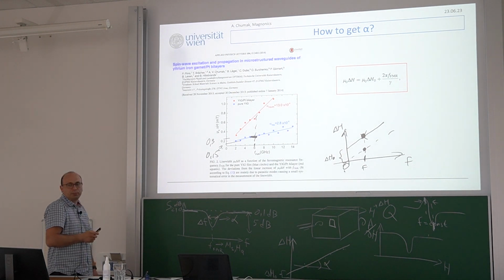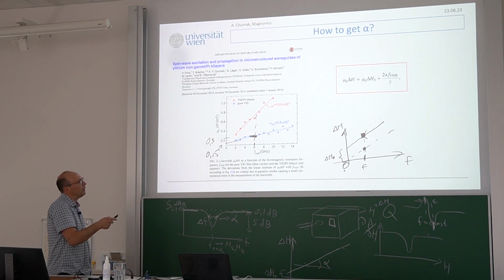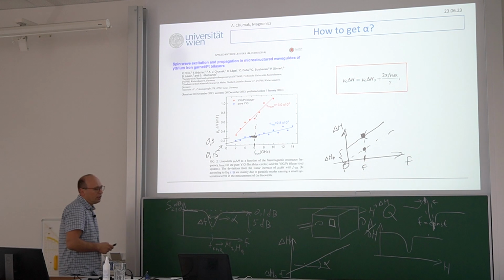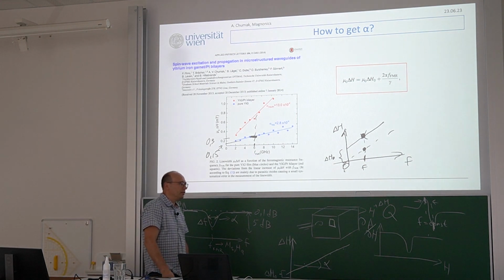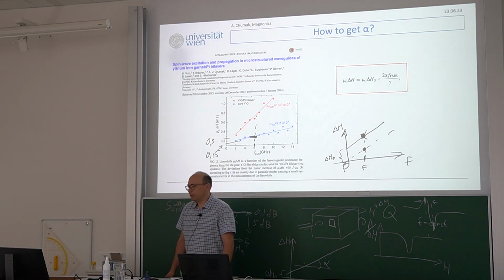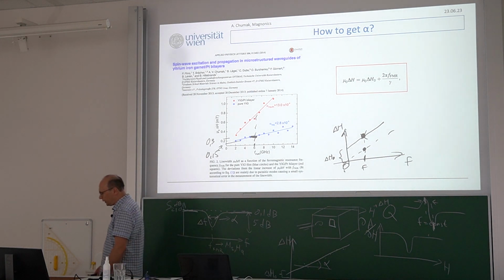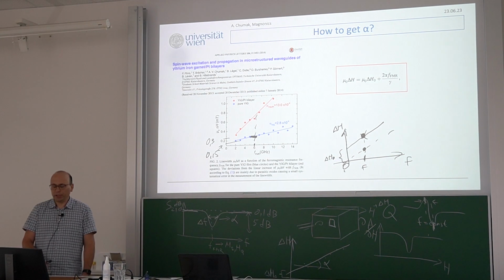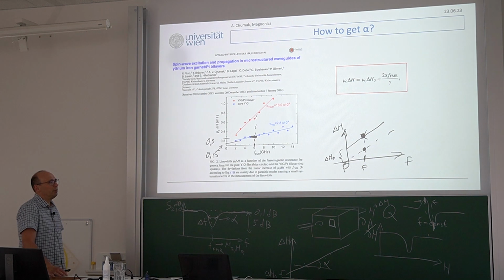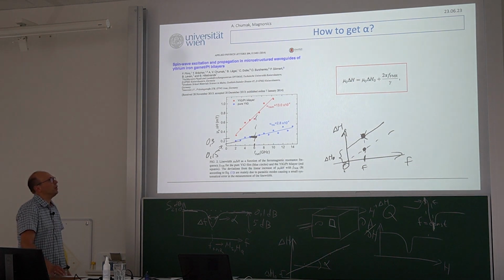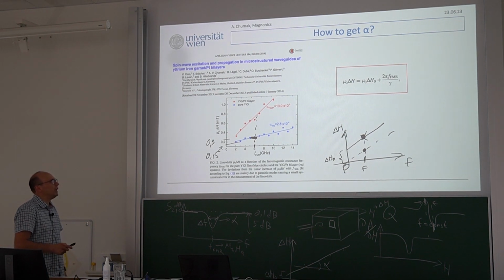What else you see in this picture is that when you put platinum on top of YIG, spin pumping will take place, a so-called mechanism which increases damping, but there are also other mechanisms, for example eddy currents generation, maybe partial proximity effects, that platinum is maybe getting partially magnetic, maybe something else.